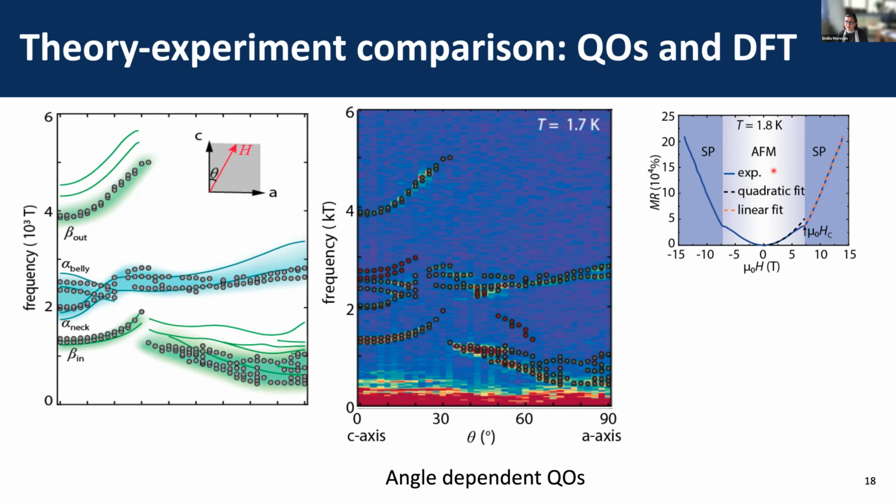One, that at low fields, the magnetoresistance is quadratic, but it deviates from this quadratic field dependence as it approaches the magnetic ordering transition at about 7 Tesla. And even with the largest magnetic fields that I'm showing in this measurement, the magnetoresistance continues to increase in a non-quadratic manner, and it doesn't saturate.